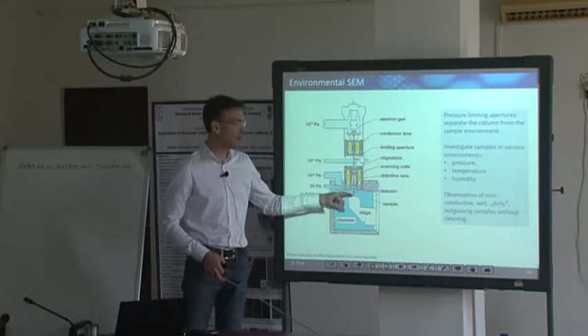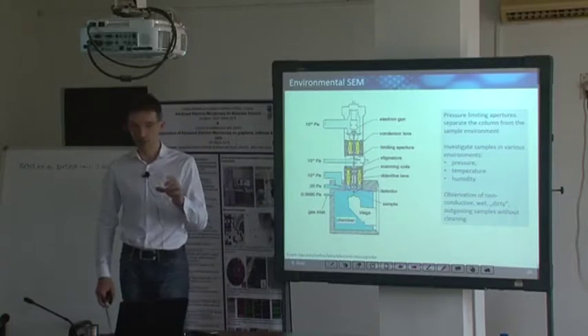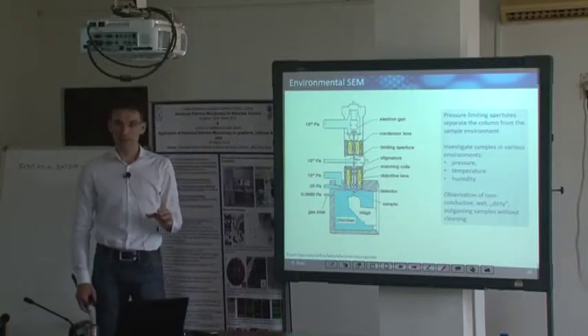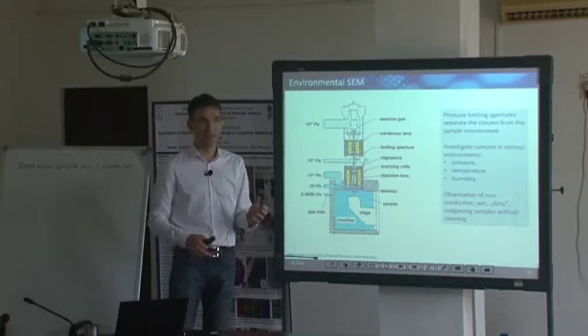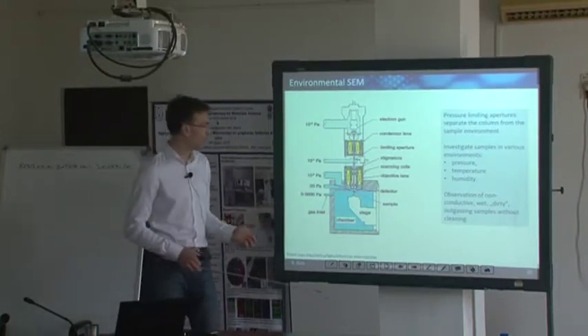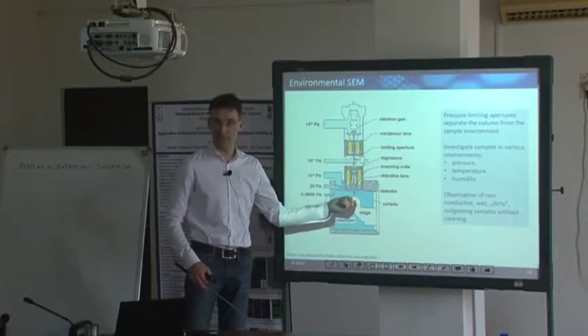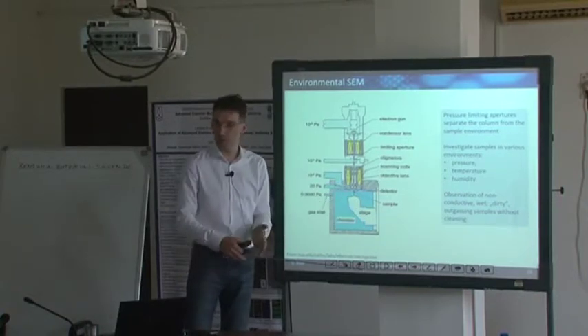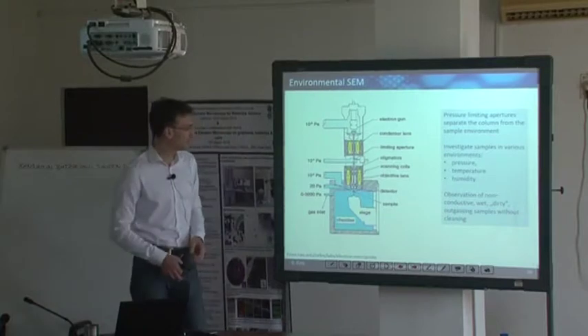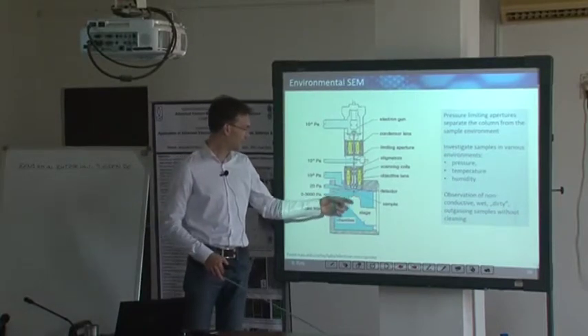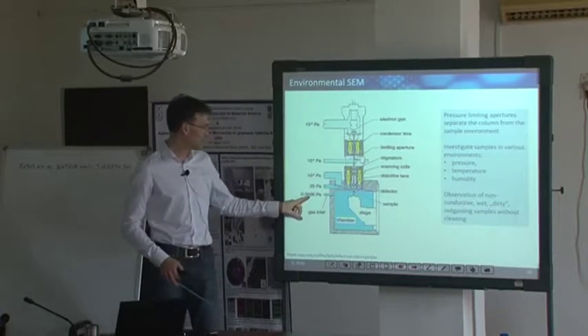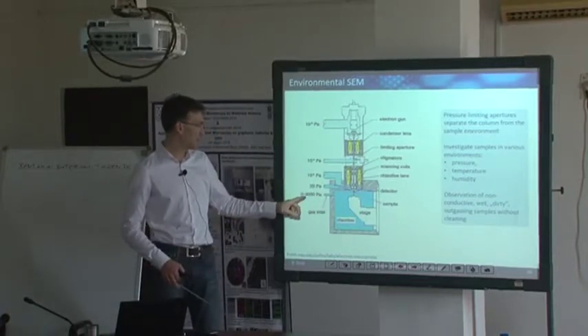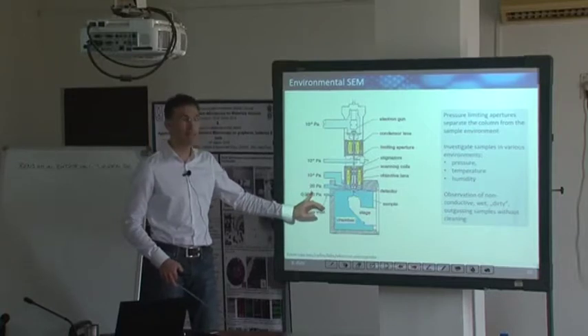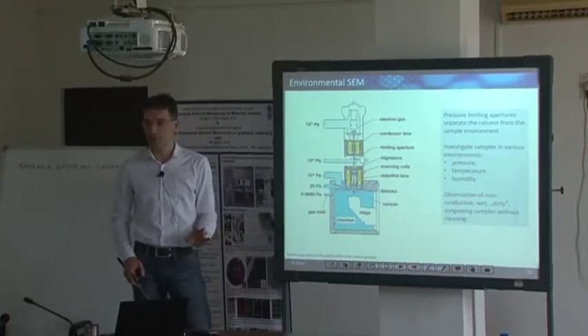But nonetheless, 30 kilo electron-volt electrons are able to penetrate through already a pretty thick layer of gas with negligible or very low loss of resolution on your sample. Any inelastic and elastic scattering would cause a broadening of your beam in a scanning electron microscope, but up to certain pressures. You can see, in this particular case, it goes up to 3000 Pascal. This is 30 millibar. 30 millibar is not a really high pressure compared to 1 bar atmosphere, isn't it?